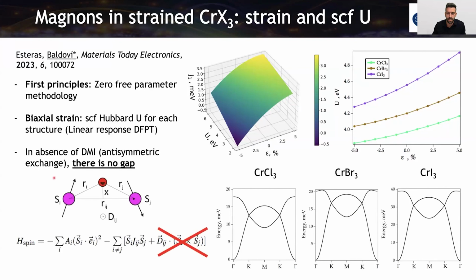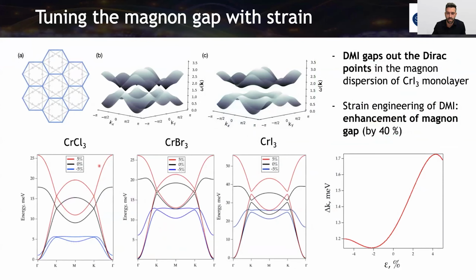With this, we could observe, when we have here the spin Hamiltonian, so here is the single ion anisotropy, we have the isotropic exchange interactions, and the Dzyaloshinskii-Moriya, that in this case is cancelled. We cancel it in the calculation, and we observe the formation of the Dirac cones for the chromium chloride 3, chromium bromide 3, and chromium iodide 3. But then when we activate the Dzyaloshinskii-Moriya interaction, is this 0% here in chromium iodide 3, these black lines, we can observe the opening of a gap.